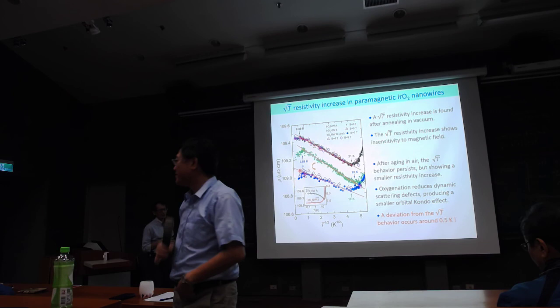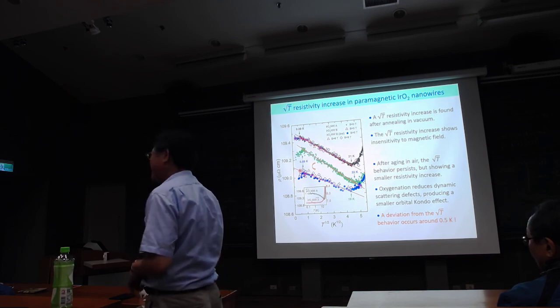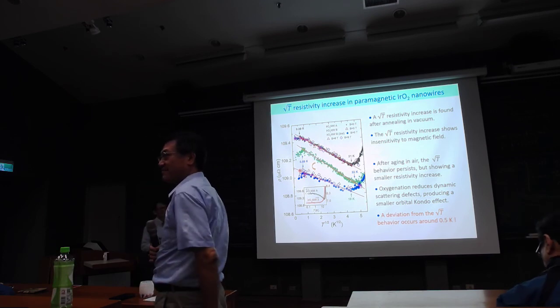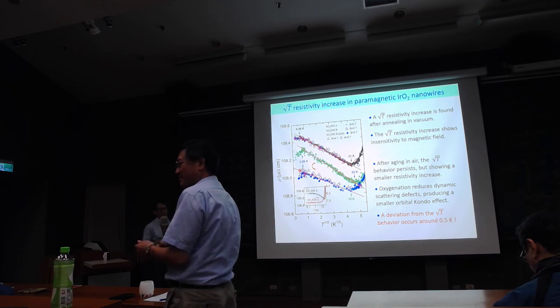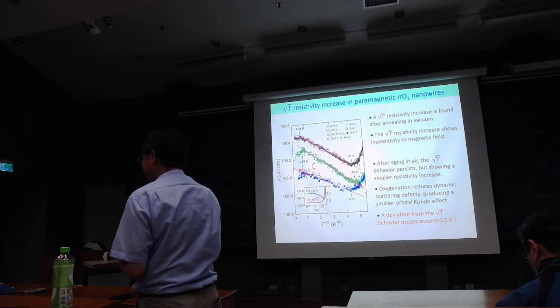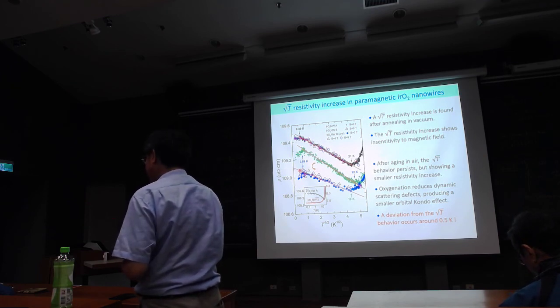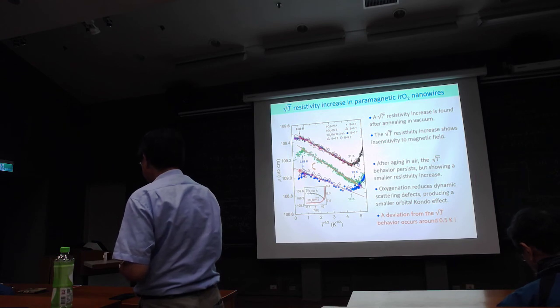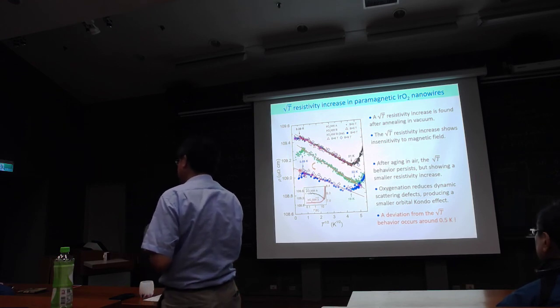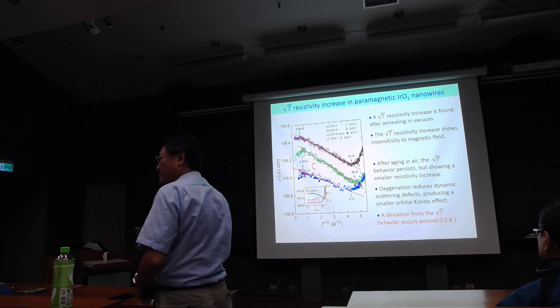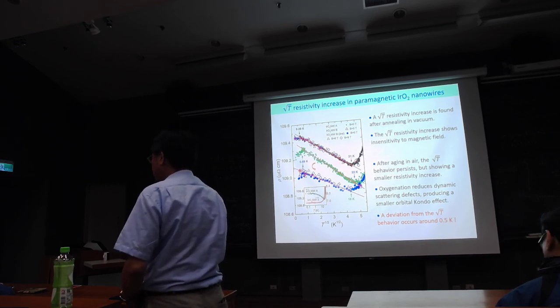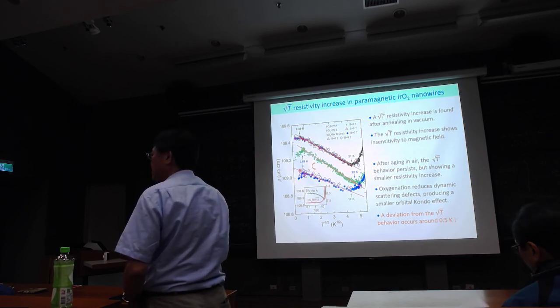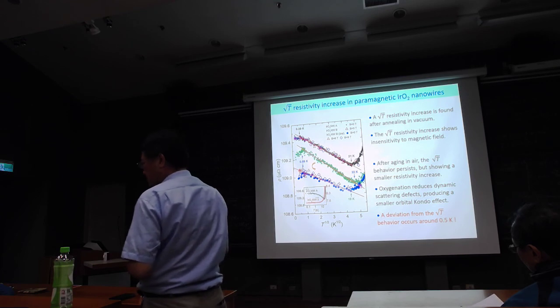So these samples are actually quite clean. They are almost single crystal. So you want them to be clean, and then there's no or very weak electron interaction. But on the other hand, because they're so clean, you want to make the sample very small, a narrow wire, so you can have a high resolution to measure resistivity.